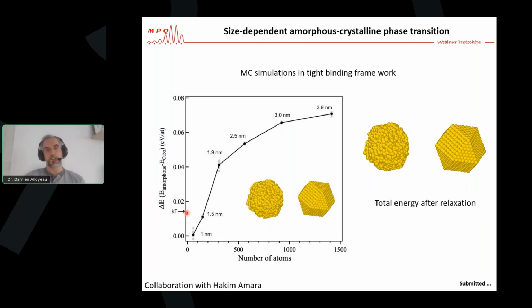So clearly these results indicate that there is a size-dependent amorphous-crystalline phase transition in gold systems, and this result is due to the thermodynamic equilibrium of gold. It's a size effect on the structural properties of gold.